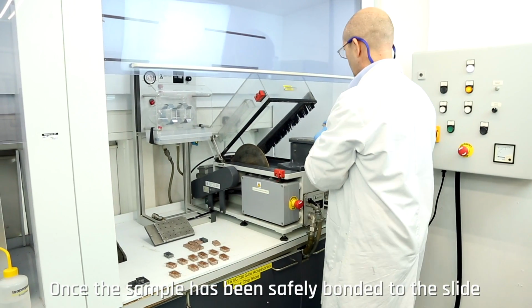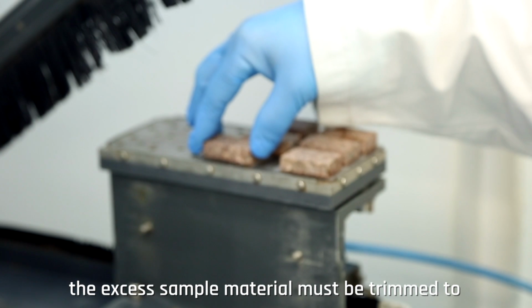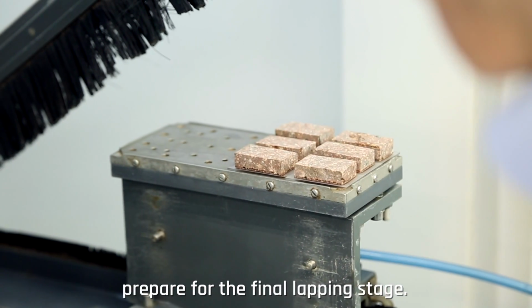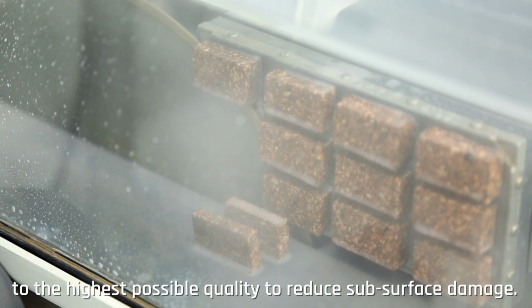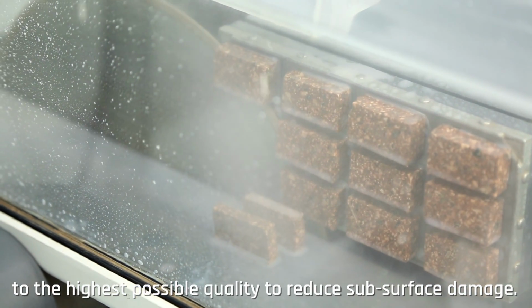Once the sample has been safely bonded to the slide, the excess sample material must be trimmed to prepare for the final lapping stage. The thinned rock sample should be as thin as possible to reduce lapping time and the cut kept to the highest possible quality to reduce subsurface damage.